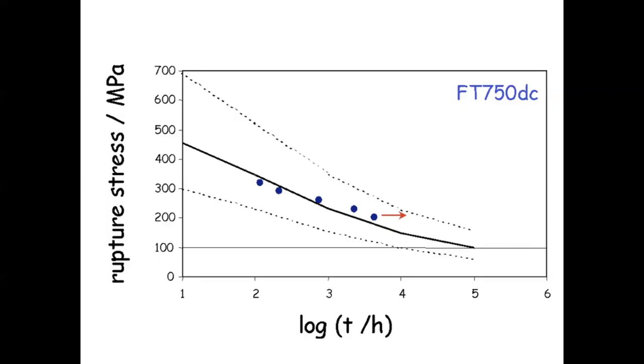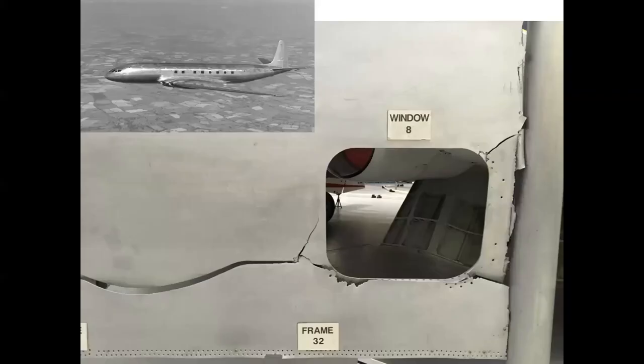So you can even have a neural network where you feed in the structure as opposed to other parameters like composition and heat treatment. Now, fatigue is a very, very important problem. And the whole reason why Boeing became a prominent company is because we had the Comet disasters in Britain, where we had these fatigue cracks forming at stress concentrations on these windows and the rivets near the windows. This was the first civil jet aircraft ever, okay? And you could fly above the weather and so forth and so on. But 3 of them crashed, and the reason was this fatigue failure, and that established the standards by which aircraft should be produced. So you have an aircraft on the ground, which is constantly being pressurized, depressurized, and simulated flying before you put aircraft into the air.